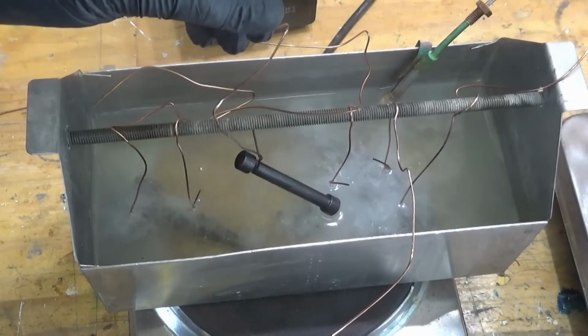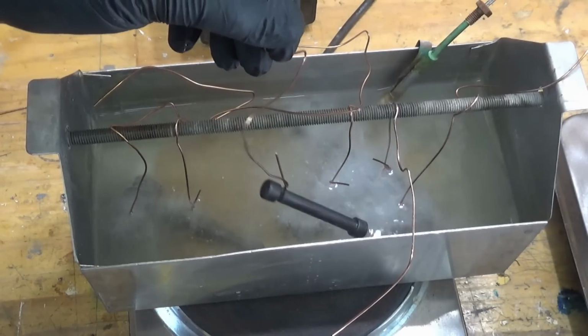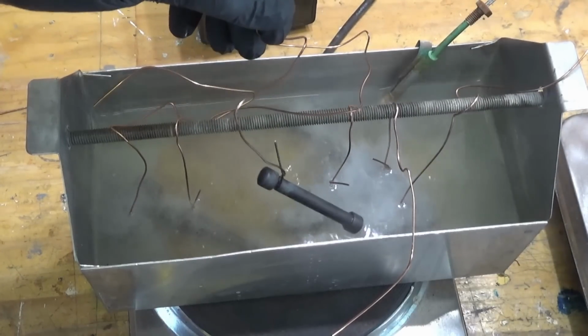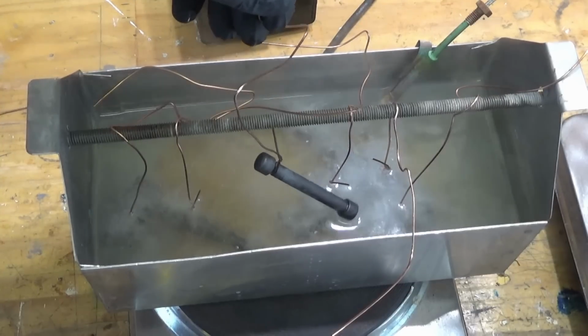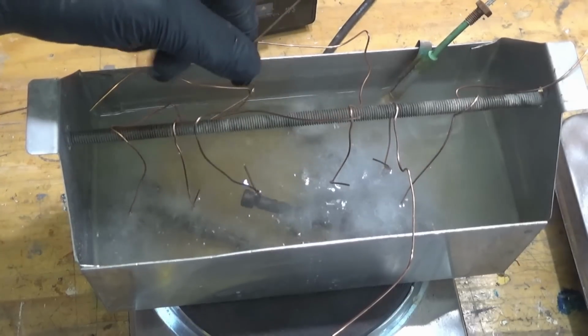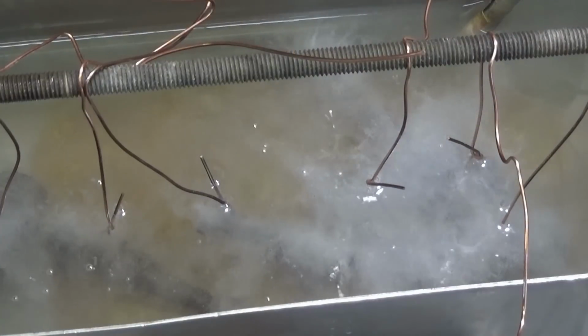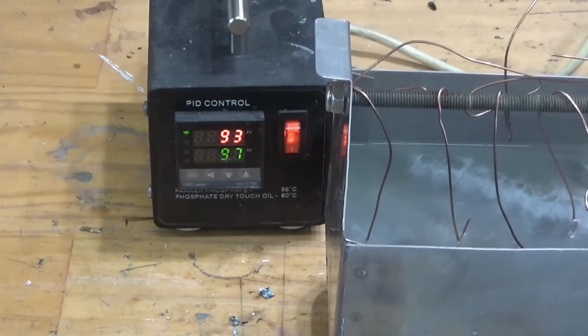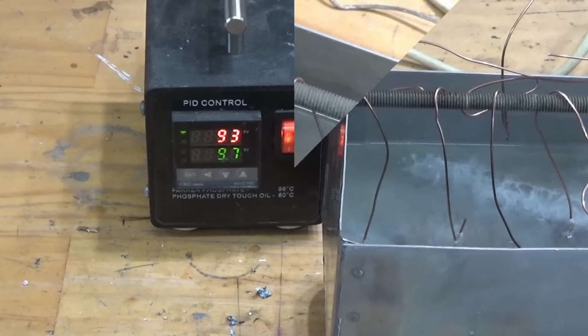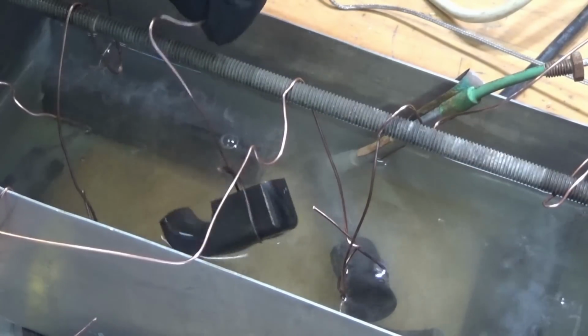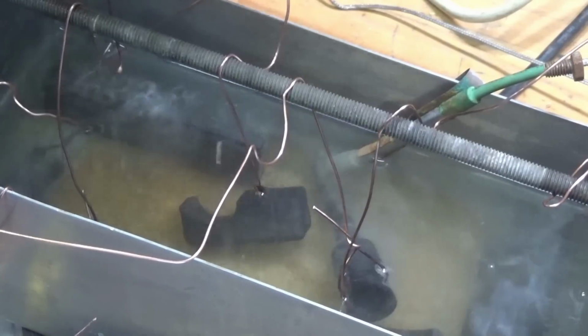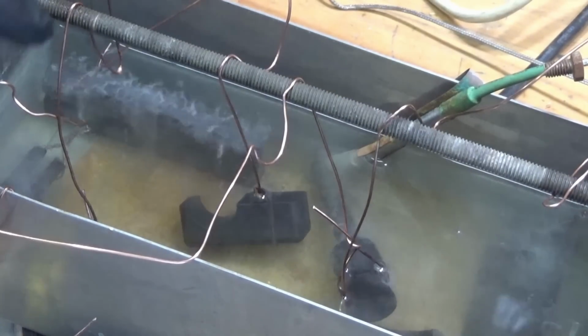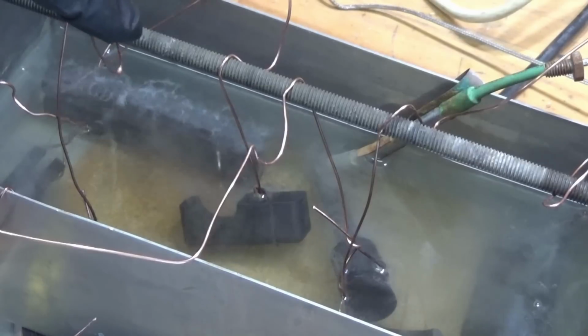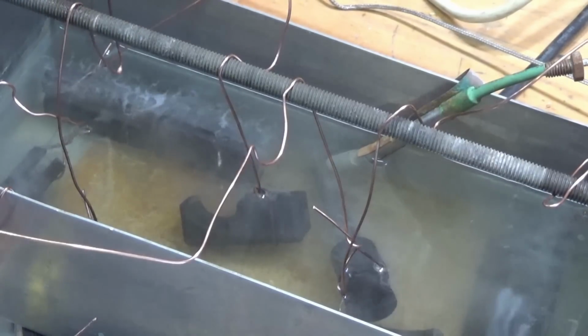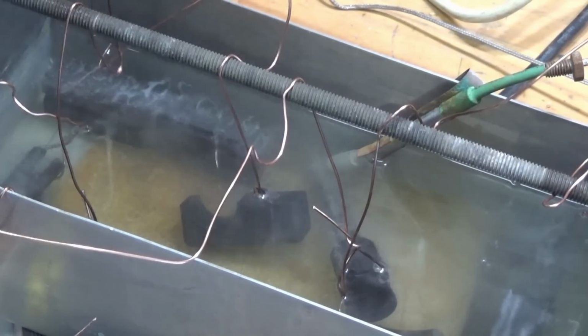After about 3 or 4 minutes, you can see the surface is now quite black, and we get a good thick coating if we leave that in there for around about 10 minutes, but 15 is probably maximum. So this is one of the parts I put in first, and it stopped fizzing. That usually tells you that the process is done. This comes out now, gets a cold water rinse, and then it goes into a soluble oil which will absorb into that coating.